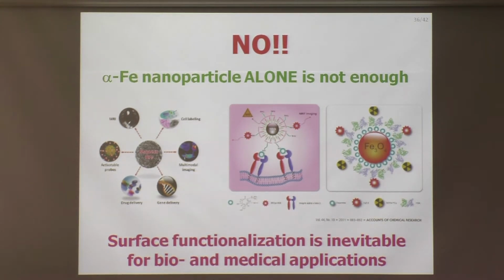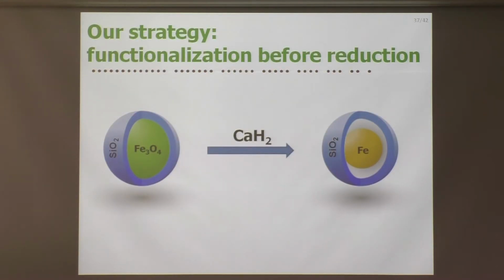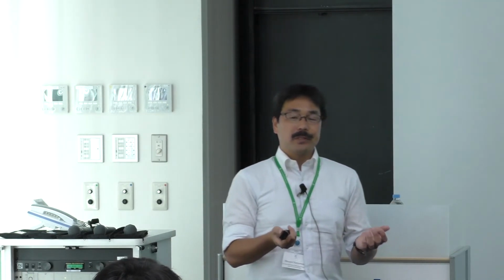We decided to develop a method for surface functionalization. As I repeatedly said, we can prepare alpha iron nanoparticles coated with SiO2. The important point is we can achieve this at low temperatures—in this case, 200 degrees Celsius, which is not so high, even for certain classes of organic molecules.